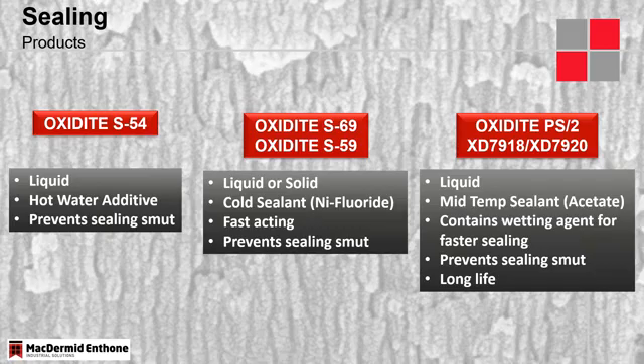Sometimes it can become quite tenacious. So for the hot water seal, we have an additive here that goes into the final rinse at very, very small concentrations. The Oxidite S69 and S59 are nickel fluoride cold sealing products, again as a liquid or as a powder product. And then the nickel acetate or medium temperature products here, we have two. The PS2 is really developed as a pre-seal, which is then followed by a nickel fluoride seal for the final sealing.